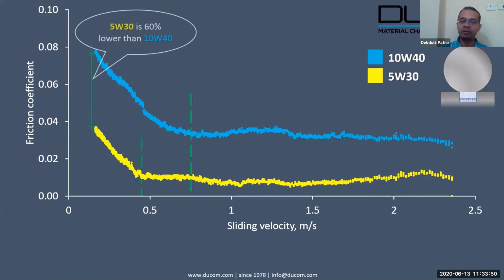This is the test data from a tribometer with two different oils. The blue one is the high viscosity 10W40. The yellow one is the low viscosity engine oil 5W30. As you see, the Stribeck curve tells us that the friction coefficient is not a single value, but depends upon your operating condition. You can see that data from the machine suggesting a typical Stribeck curve. More importantly, the yellow curve is 60% lower than the blue curve. The difference between these two oils is close to 50-60%, so 0.08 and 0.04 from this test data.